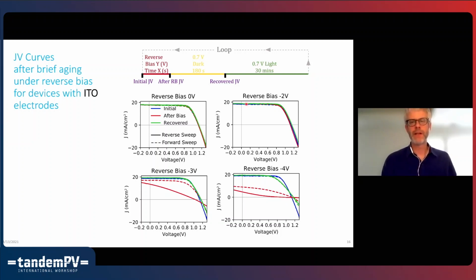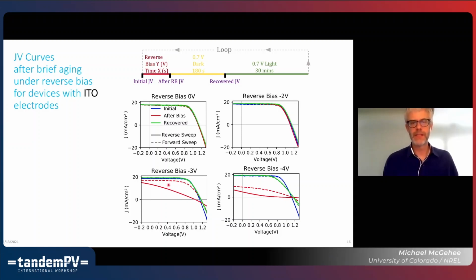And you'll see that for this particular solar cell, aging at -2 volts did not cause a problem. However, aging just briefly at -3 volts really substantially changed the IV curve. And introduced a lot of hysteresis. The dashed is the forward sweep, and solid is the reverse. And then you see -4 volts almost completely destroyed the solar cell.